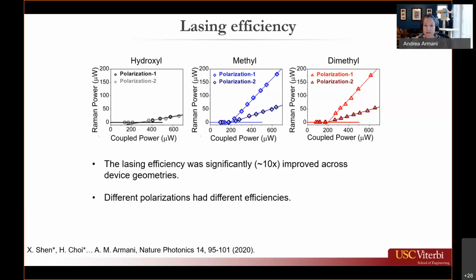And additionally, the efficiency is incredibly low, which is what has been seen in all previous work. When you have the methyl and the dimethyl groups, you see a significant increase in efficiency with either input polarization. Additionally, you do see that threefold increase with one polarization over another polarization. And you also see a change in threshold.